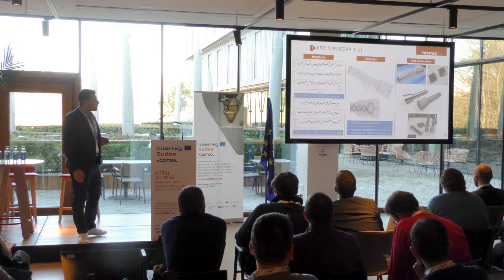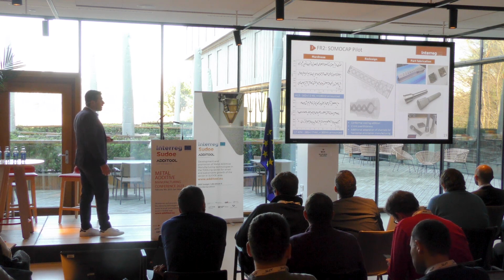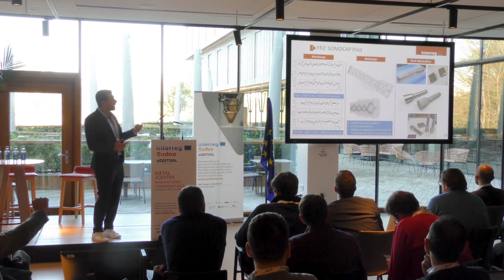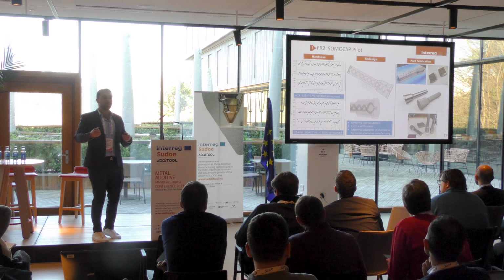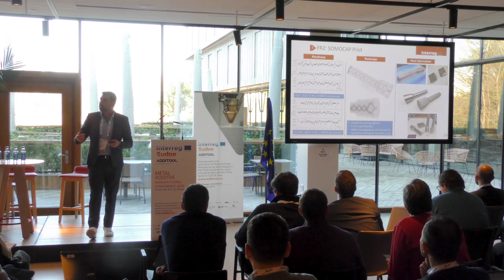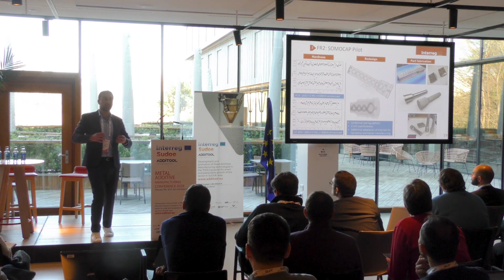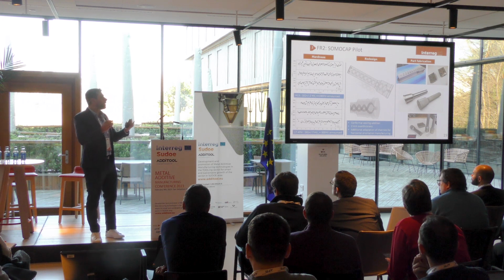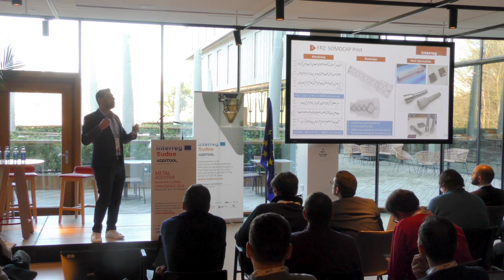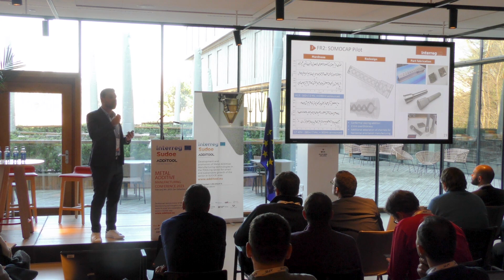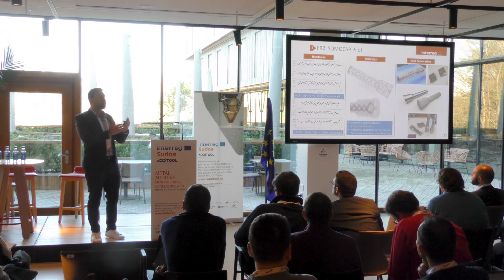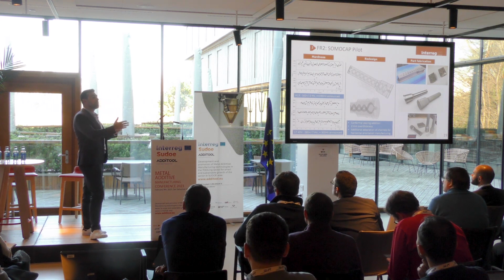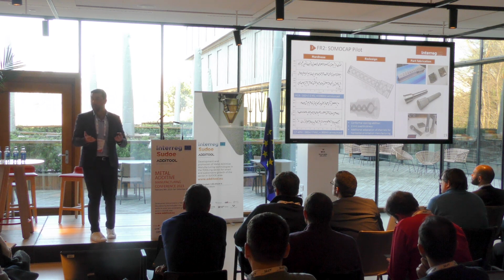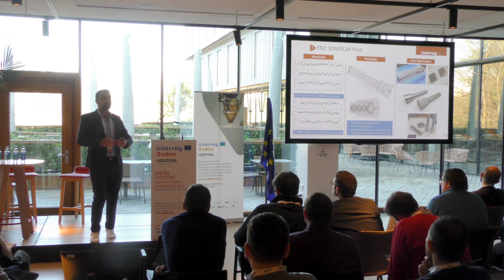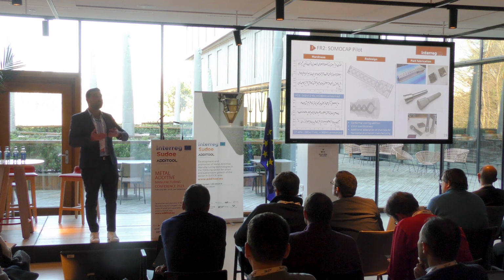Just some words about the Rapidia technology. During the project we discovered a new technology. It's not a filament, but an aqua paste, an aqua gel, a paste where the load of material is very high. In a filament you cannot exceed more than 50% of powder; with an aqua paste you can increase to 90%.